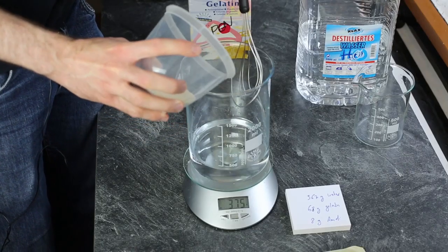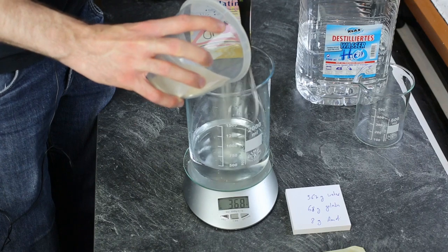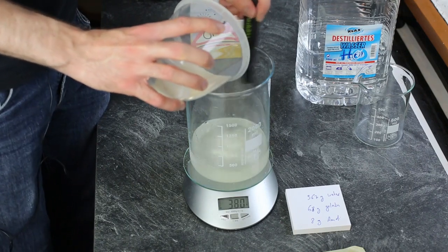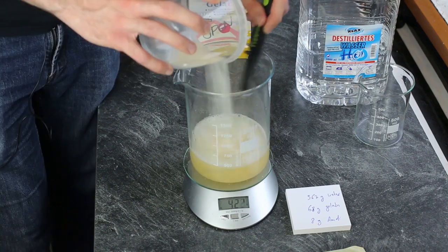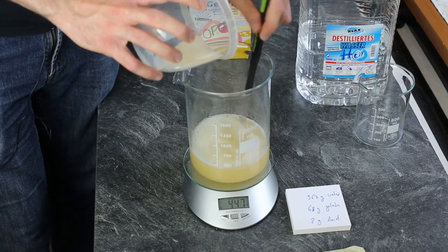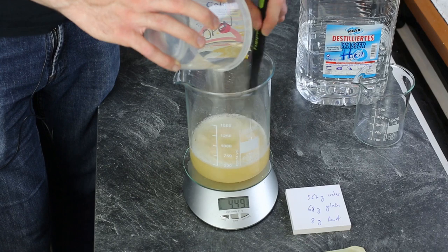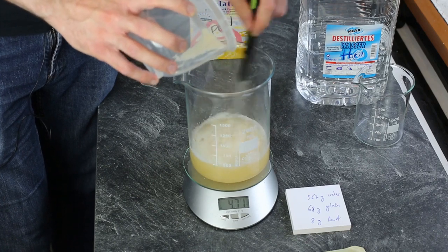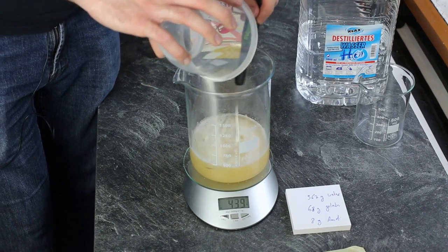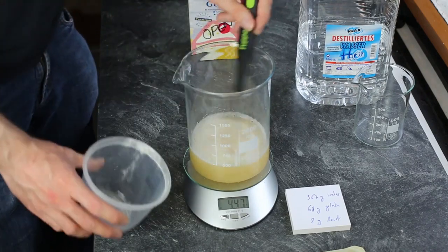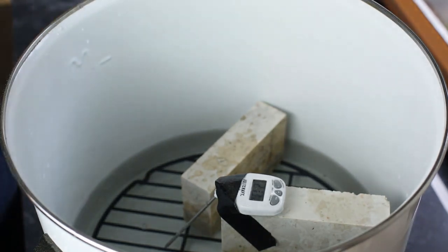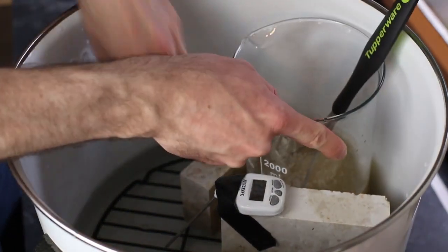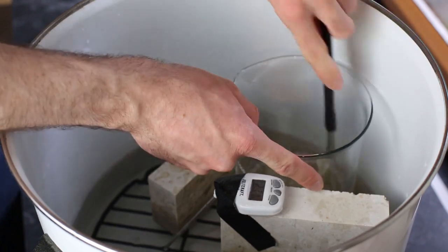So I put 367 grams of cold water into a beaker. While stirring with a whisk, I slowly pour 68 grams of gelatin powder into the solution. After a few minutes, the gelatin will get very thick. Now I place the beaker into a water bath. I use an electric canner for that, because it can be set precisely to a certain temperature. The temperature of the water bath will slowly rise to exactly 40 degrees.